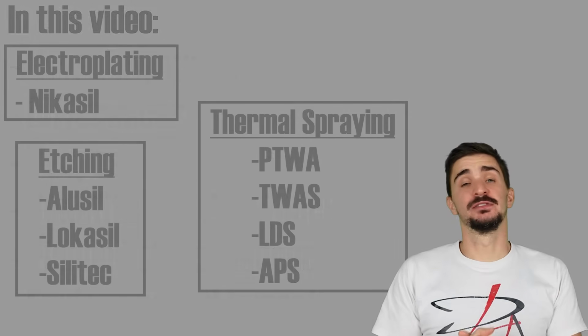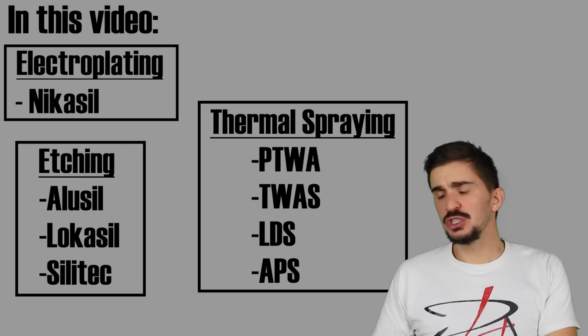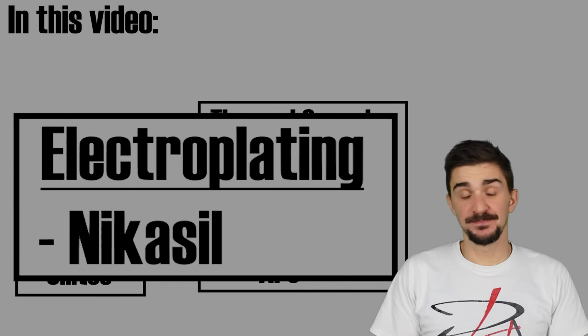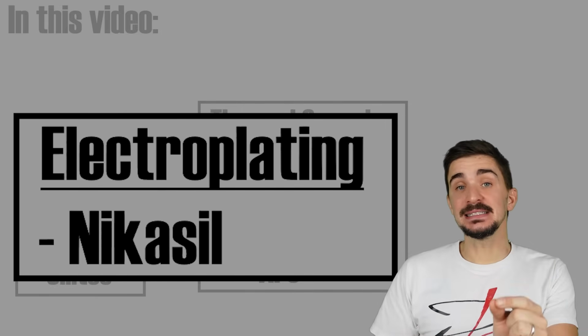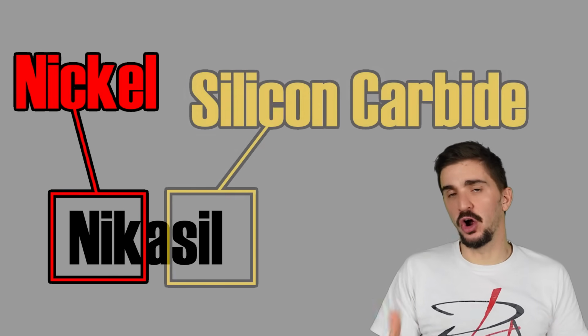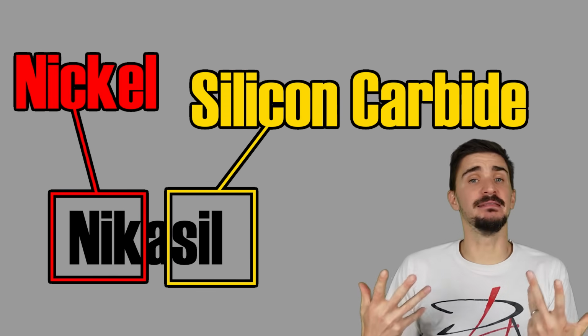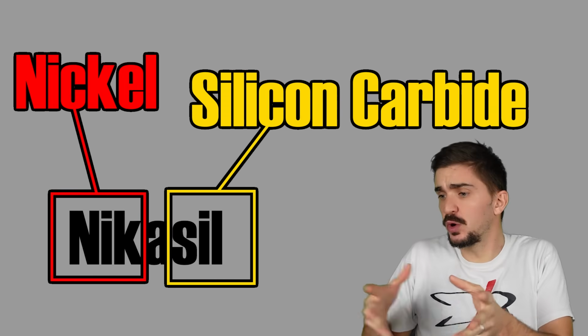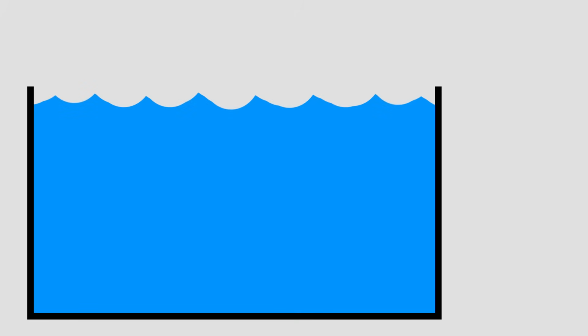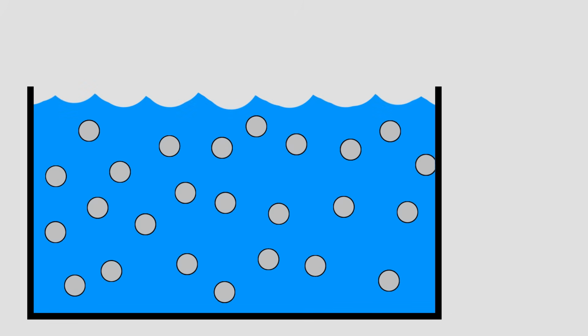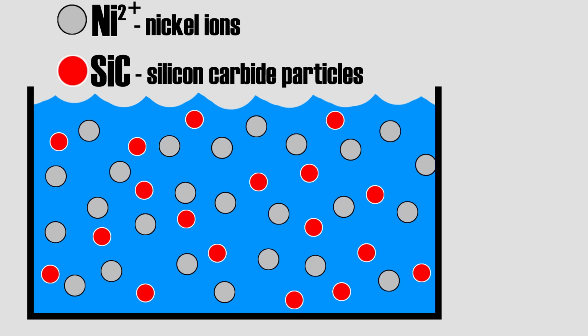One of the first cylinder coatings to be used in mass production is also probably one of the most famous. It's called Nikasil. Nikasil stands for nickel silicon carbide, and it's essentially an electroplating process, and so it works just like any other electroplating process. So what we have is a solution or a bath, basically a liquid, which is filled with nickel ions and silicon carbide particles. Silicon carbide is essentially a ceramic which is extremely wear resistant.